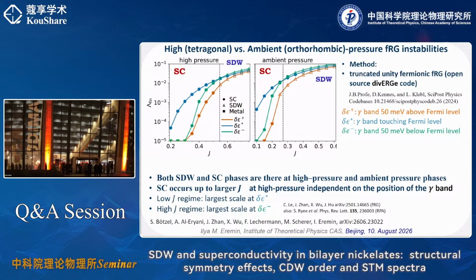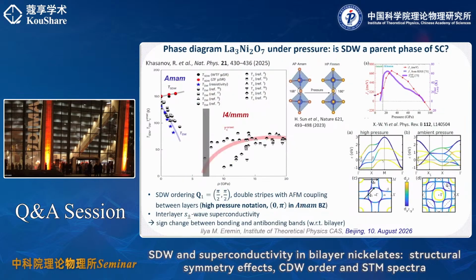So in the beginning, we did not start from the picture where you showed the Fermi surface before, right? Because when we see this Fermi surface, it looks very much like C4 symmetry. Well, in reality, it isn't. There is a structure of asymmetry, but it's so tiny. The difference between A and B is so tiny. Actually, you don't have a C4 symmetry. We just plotted it here for convenience, but they are not exactly identical. Now I see, it can actually get twisted a bit. But this is enough. This already gives you a difference between (pi, 0) and (0, pi). It's hard to see with bare eyes, but if you do the calculation, you immediately see that (pi, 0) and (0, pi) are different. If the Fermi surface is not C4 symmetric, then there is no problem. You immediately see that they are inequivalent, and that is why the system immediately knows which order it wants to set.